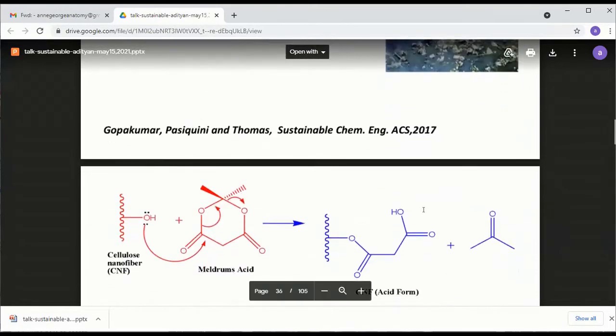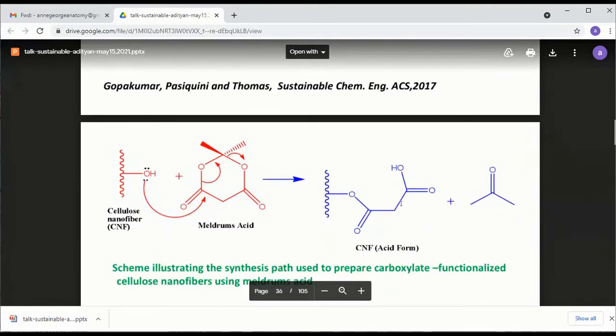I will show you a slide, but we did some chemistry in order to make the filtration process very efficient, removal process very efficient. We did some chemistry on the surface. This is cellulose, nanocellulose. My PhD student made nanocellulose, and we did a green chemistry. We reacted with Meldrum's acid. Very simple reaction. And we introduced CO minus group on the surface of nanocellulose. Very simple chemistry you can do in a BSc laboratory.